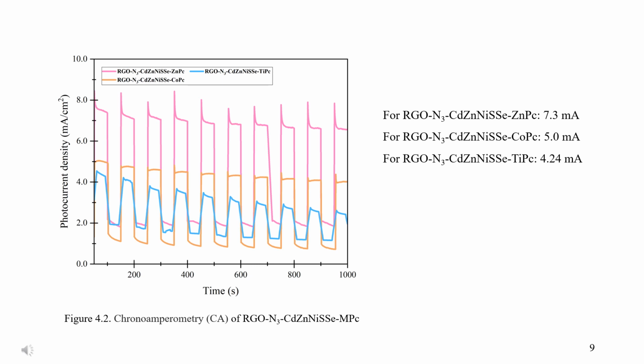According to Figure 4.2, the reduced graphene oxide, cadmium, zinc, nickel, sulfur, selenide, zinc phthalocyanine electrode gave the highest photoresponse, which is 7.3 milliamperes. At the same time, this structure has high stability and low recombination. When the electrode covered with cobalt phthalocyanine was examined, it was determined that the photocurrent density was 5 milliamperes. This value is 1.46 times less than the current density created by the zinc phthalocyanine electrode.